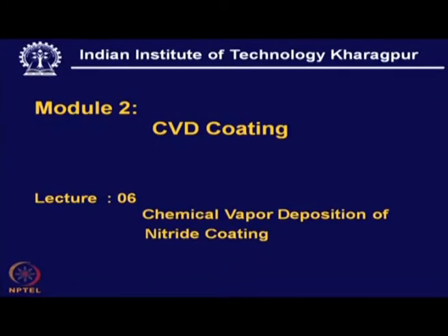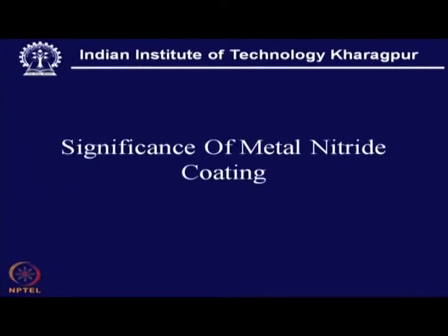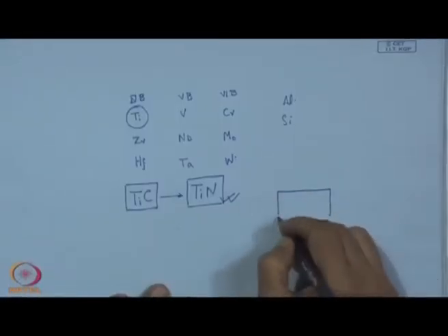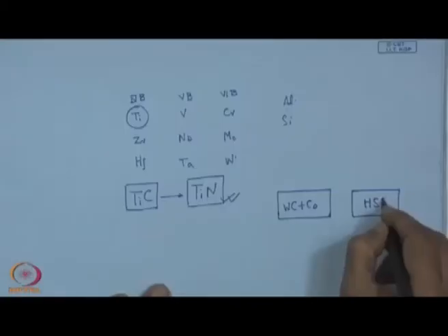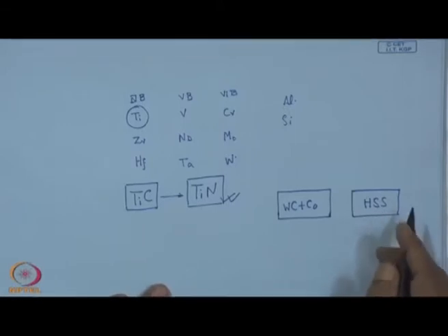So, this TiN can be used in the form of a coating over this tool substrate to give this surface property, so that we can get a high performing product. Now, this TiN, how can we put it on the surface? Here we can see this is a substrate, and say it is made of tungsten carbide and cobalt, or it can be even HSS, or say die steel, tool steel, bearing steel and many more alloyed steel, where we need to augment or enhance the surface property.